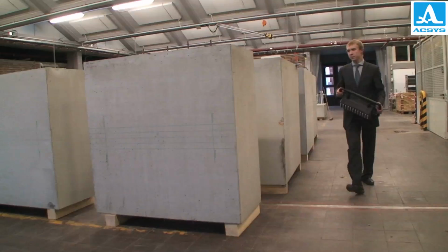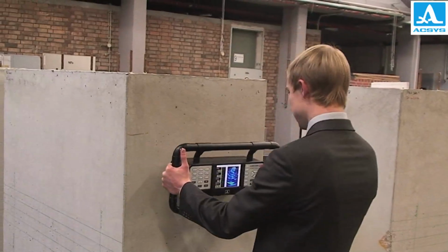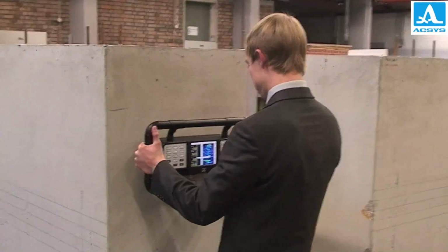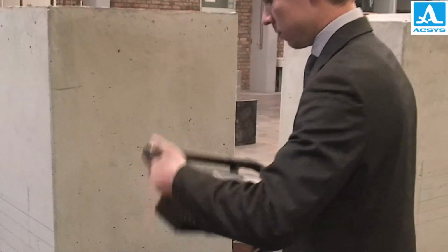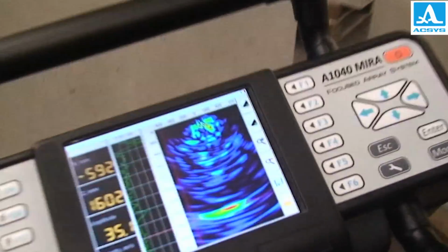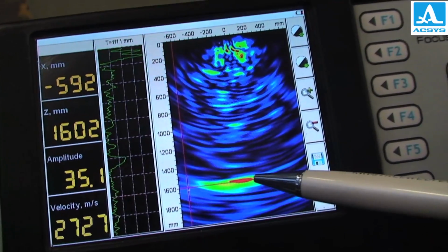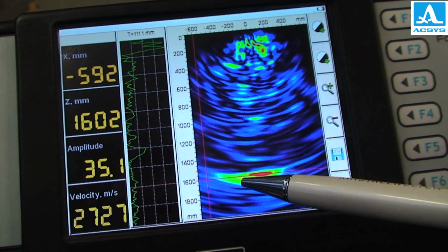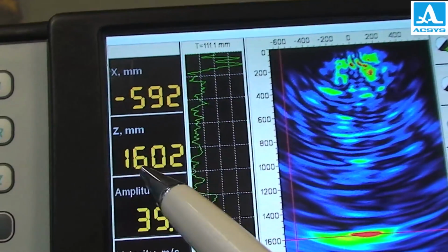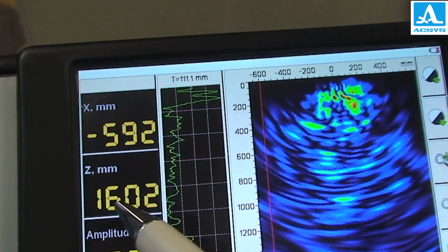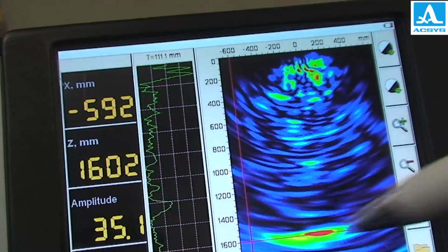Ultrasonic testing of a concrete wall panel was performed using the MIRA system to measure the thickness of the wall. At about 3 to 4 seconds after the system was triggered, the test results were displayed on the built-in screen. The bright red area in the tomogram corresponds to the signal reflected from the back wall. The thickness of the concrete wall panel is indicated by placing the cursor at the center line of the red spot and reading the corresponding depth on the metric scale on the left side of the tomogram.